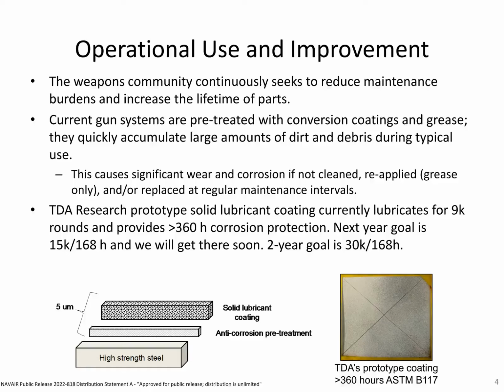Our coating system is shown very generically on the bottom. On top of the high-strength steel substrate, there is an anti-corrosion pre-treatment that is a zinc-nickel coating, and then we have a few microns of a solid lubricant coating that's based on an organic polymer with lubricious particles incorporated into the polymer. The pre-treatment is electroplated onto the steel. It's a very standard process using a brush electroplating method from SIFCO ASC.